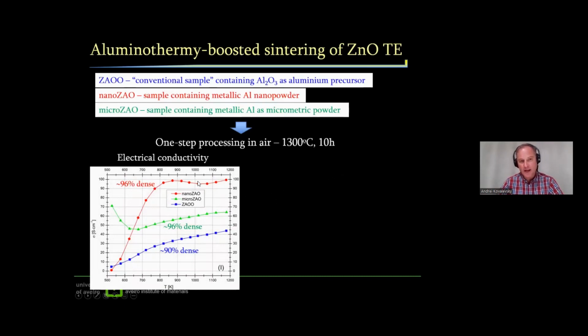We had significant enhancement, also some enhancement in density, because this local evolution of heat somehow densified our material better.